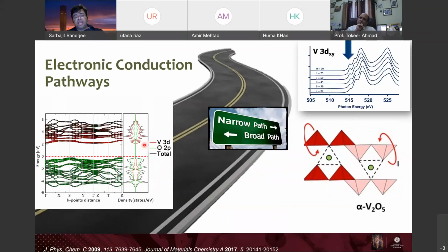So now the challenge with the electrons moving in, ionic diffusion is problematic. It comes from some fundamental ideas of crystal field splitting, like you would have studied in your basic inorganic chemistry class, right? So V2O5, vanadium in a square pyramidal environment, has this crystal field splitting, which puts a vanadium 3d xy state at the very bottom of the conduction band. Okay, so this 3d xy state, and this is some X-ray absorption spectroscopy, where we were able to figure out that this is a 3d xy state. This is over a decade ago now, and this state splits off from the rest of the conduction band.